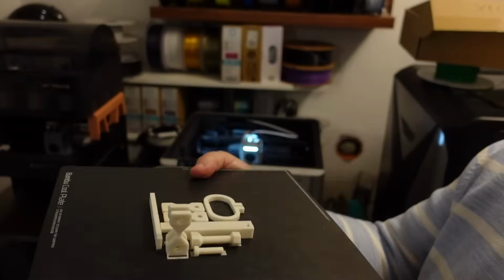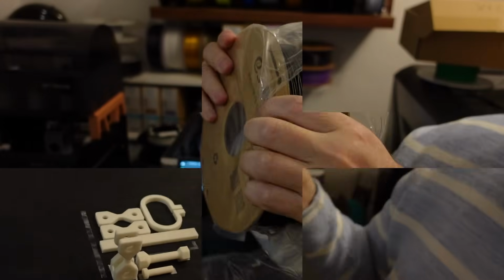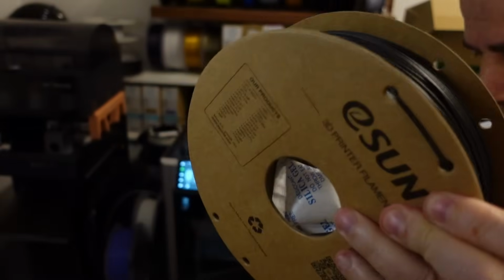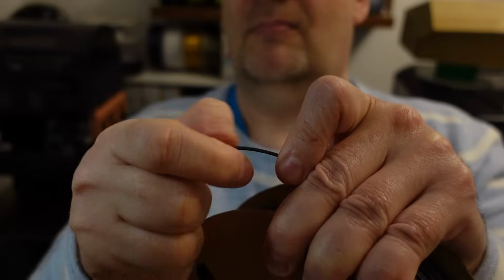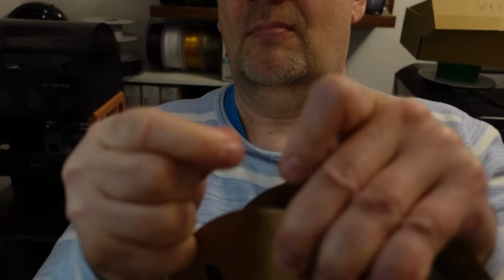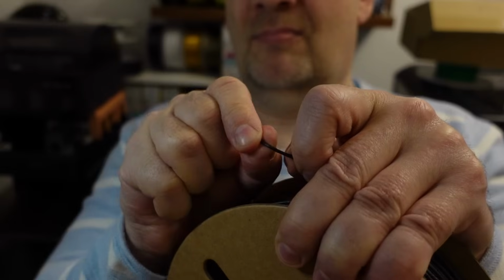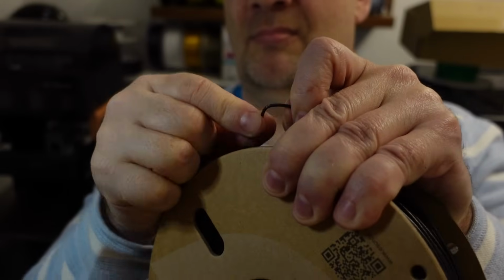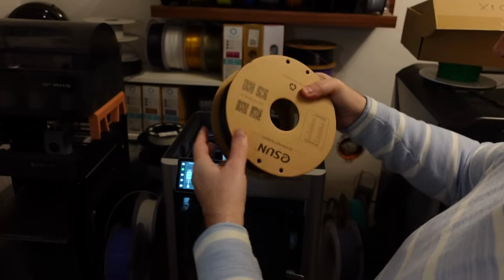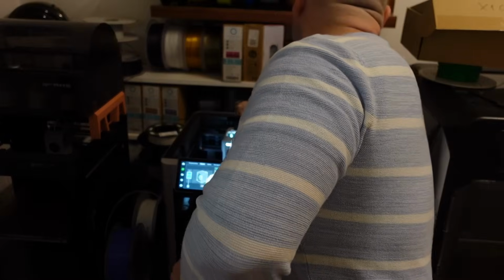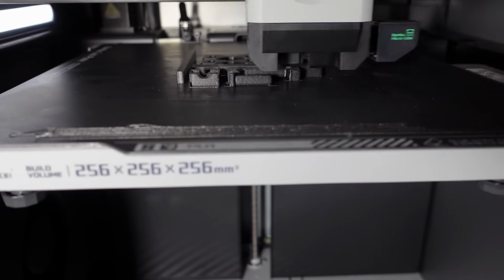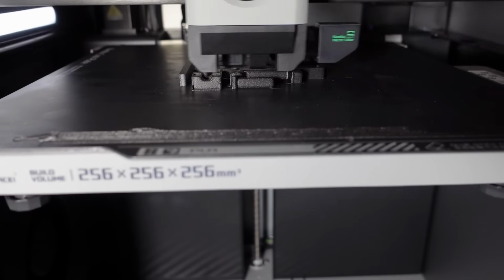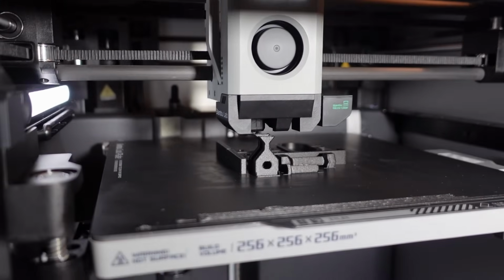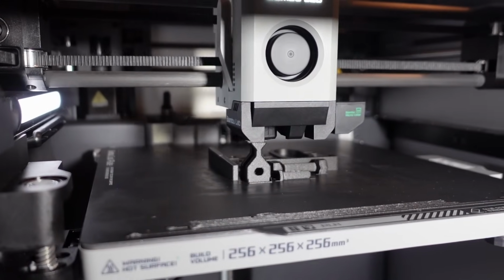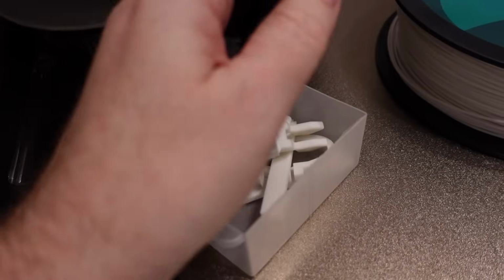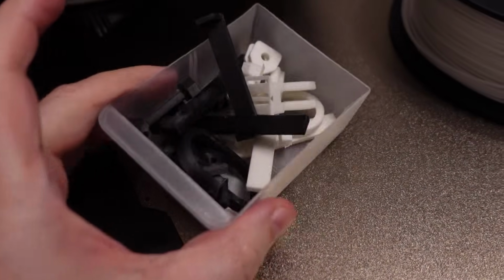And with some bending it is very easy to remove the objects. And then moving to the carbon fiber version, here the end of the filament is in the holes and immediately I check it is brittle material but less brittle compared to the glass fiber filament. And I will use here the same G-code like with the previous printing. Again some real-time footage you can see here, and really beautiful surfaces we get thanks to these carbon fibers. Objects are prepared, ready for mechanical testing.